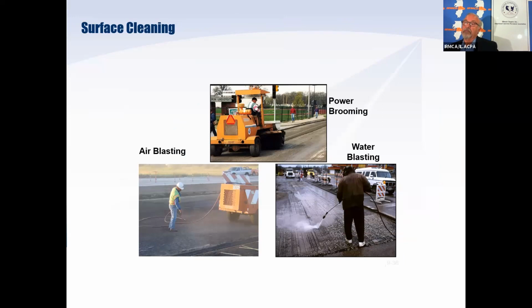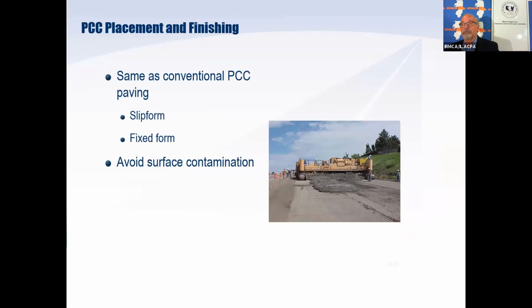So in order to get the bond that I desire and need, I'm going to clean the surface. I'm going to power broom it almost always, and then I'm going to air blast it or water blast it depending on the circumstances. I can place it with a slip form paver. If it's in an urban area, I can form pave it. I can put down with a vibrating screed. If I wanted to, I could put a short area down, striking it off with nothing more than an edge tool or a strike off tool.